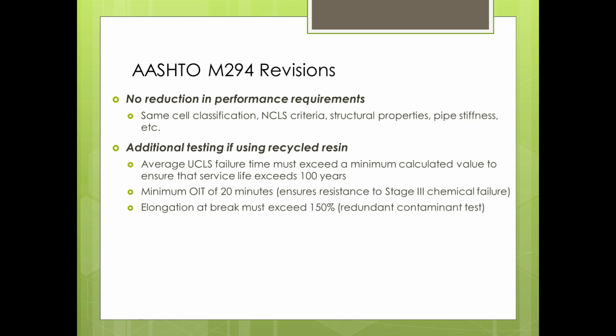If a manufacturer chooses to utilize recycled resins, they will obviously have to do the UCLS test, the ASTM F3181 test that I showed from NCHRP 4-32. That must exceed a minimum calculated value to ensure a 100-year service life. There will be an additional test to test for antioxidants in the recycled blend, which is called the OIT test,